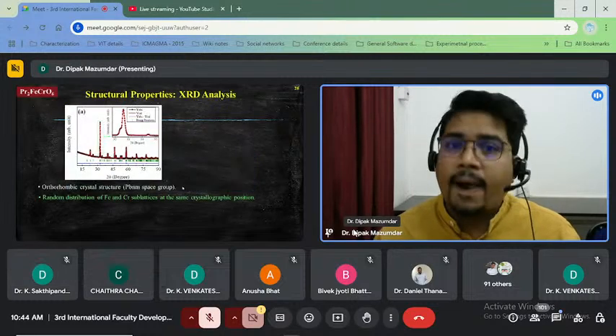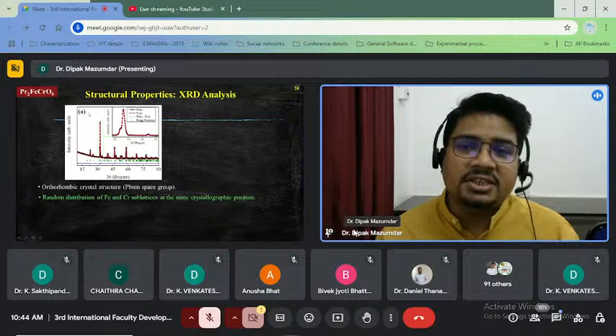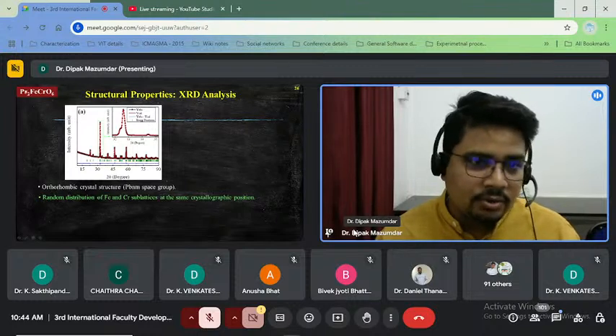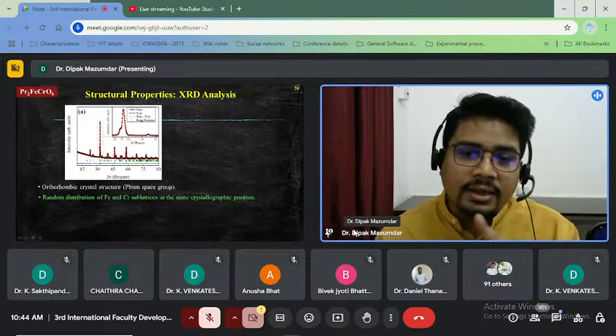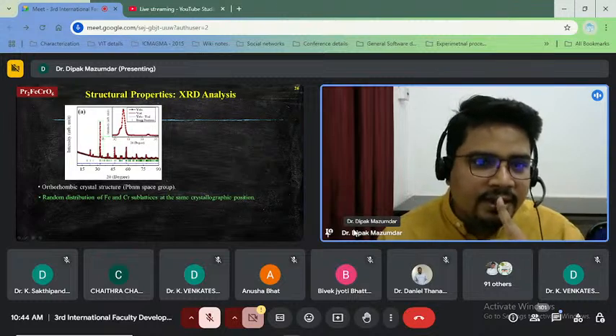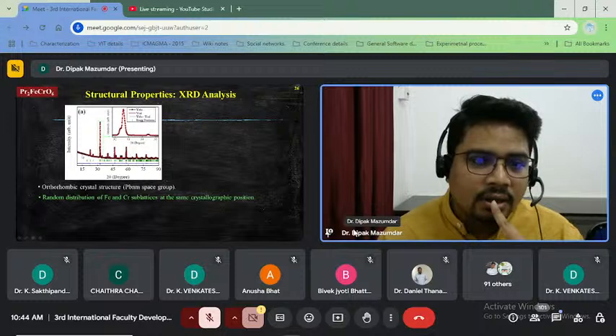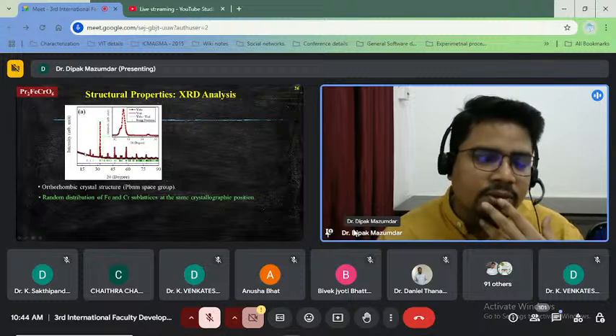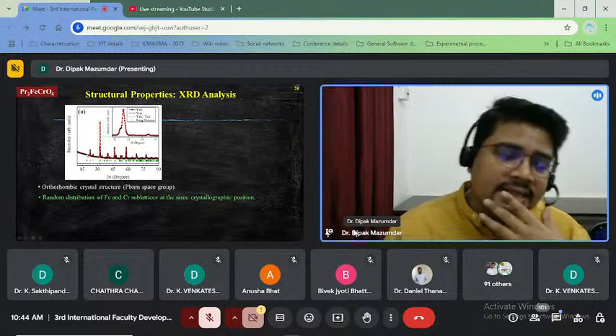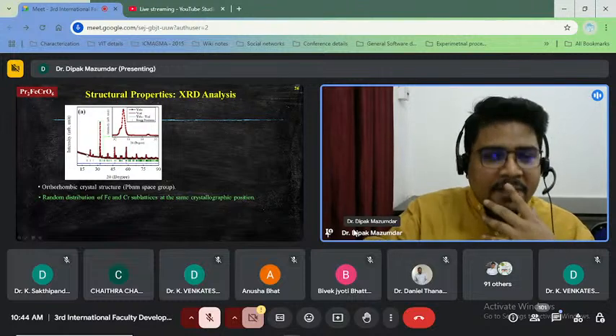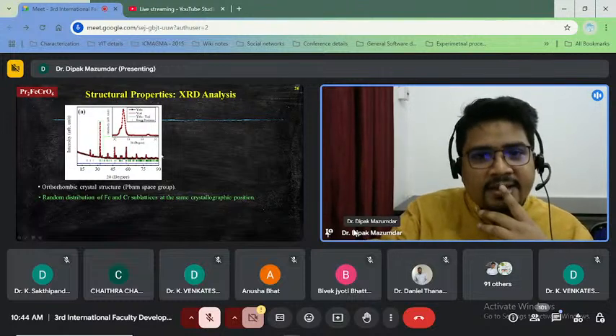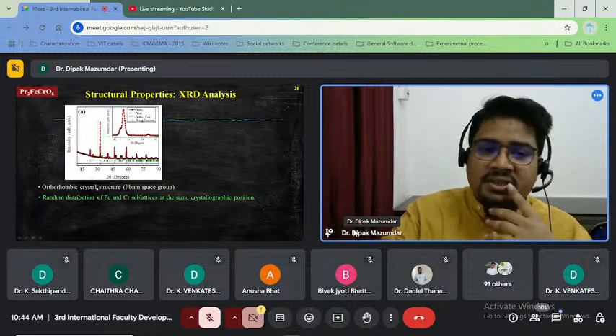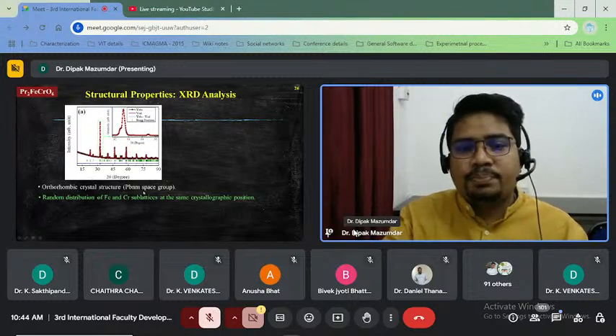So you can see this is the crystal structure of this compound Pr2FeCrO6. Earlier I mentioned that there should be a small peak around 20 degrees, but this peak is absent here, or I can't get this peak. So it simply indicates a disordered perovskite structure, and this whole XRD data is well fitted with an orthorhombic crystal structure having space group Pbnm.